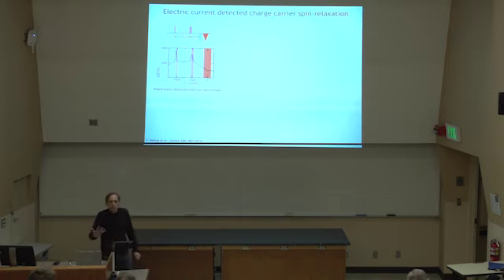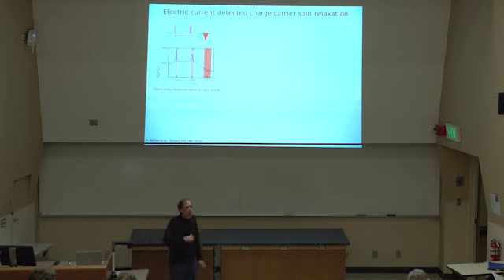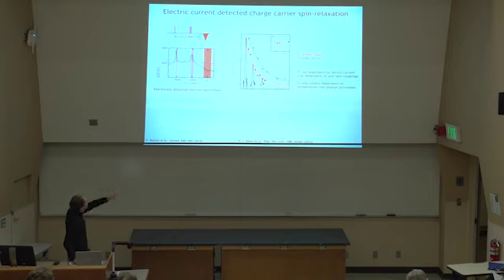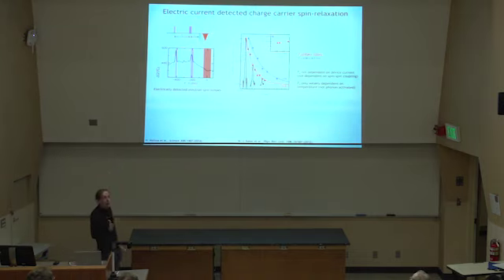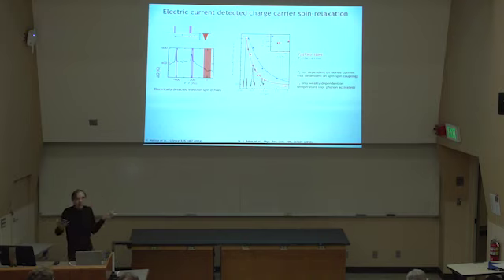Once you see a spin echo, then you can measure the echo decay. For instance, and these are two different measurements. This was actually done before we did this. We did this when we really have learned how to do it noise-free. So these echoes are noisier. But you can still determine a decay as a function of your pi half to pi pulse delay time, and therefore see the coherent decay of your coherent spin ensemble. And from this, you can derive your T2 times, the true quantum coherence times of your charge carrier spins.